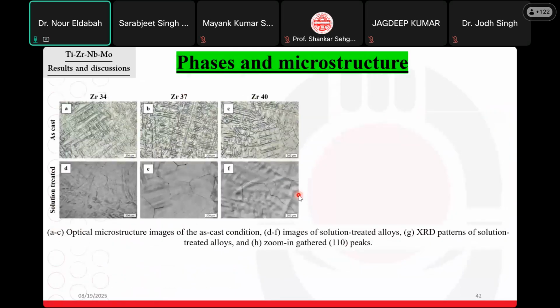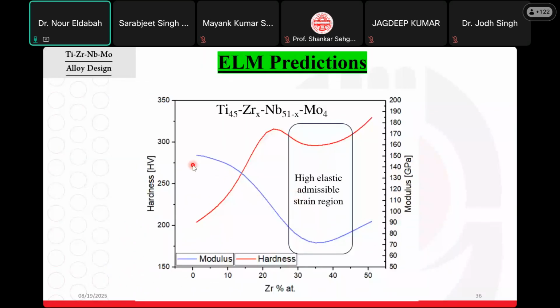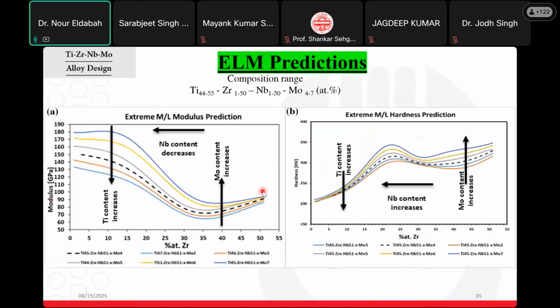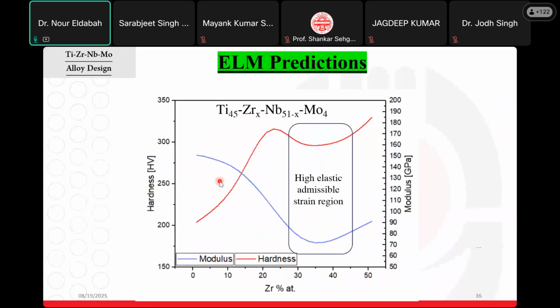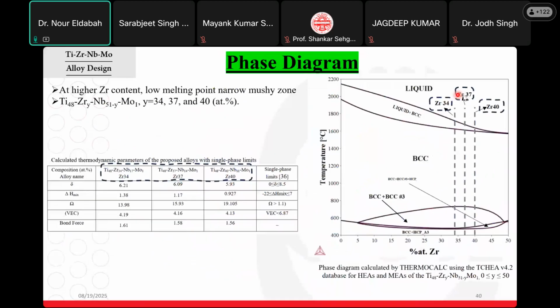Okay, the answer to this question is here. You can find that the variation in zirconium causes a drastic change in elastic modulus compared to the niobium content itself. You may vary the niobium concentration while stabilizing the zirconium, but you will not affect the elastic modulus. So zirconium was the element that most affected the elastic modulus of the alloy, in line with the melting point. Increasing zirconium strongly affects the bond force and the melting point of the alloy, so we considered it.